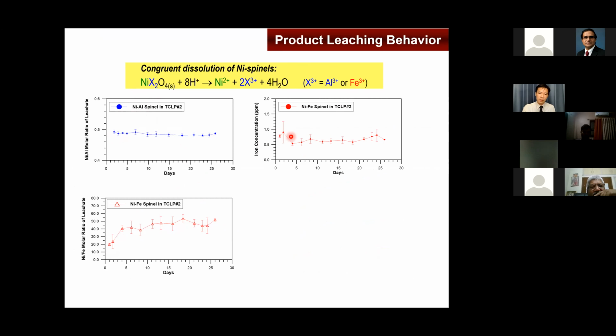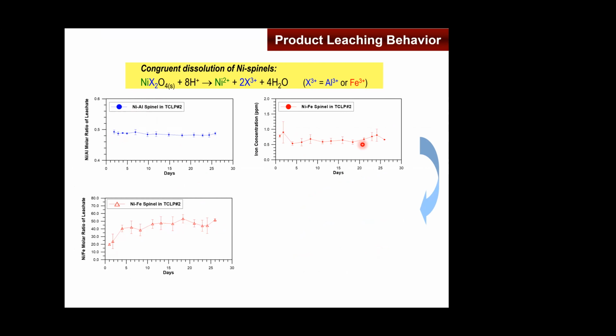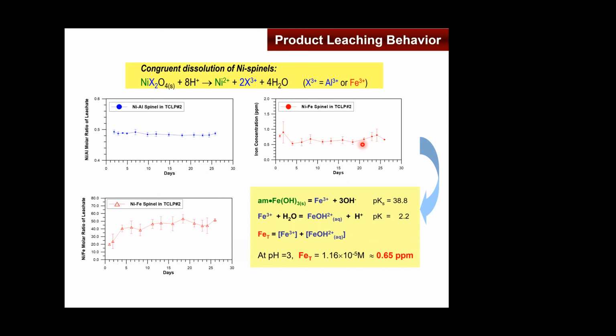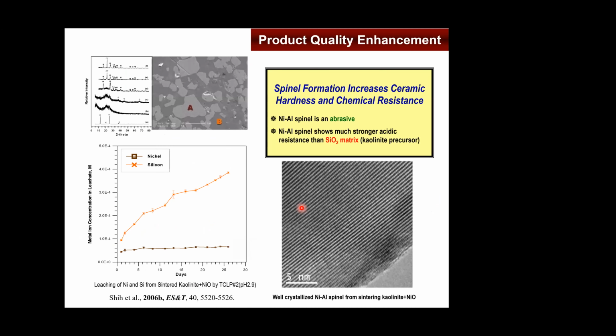And what we have to do is to really look at the iron concentration, and we go through what we call the quantum chemistry calculation. What we eventually find out is the leaching behavior of nickel aluminum spinel is congruent dissolution. But when you use iron to stabilize nickel in the spinel phase, what you will see is a reprecipitation of amorphous iron hydroxides on the surface. This is actually good because when the heavy metal is stabilized and then exposed to, say, a geoenvironmental environment for the leaching process, you actually will have layers of amorphous iron hydroxide covering the surface to protect your products, preventing the further leaching of nickel.